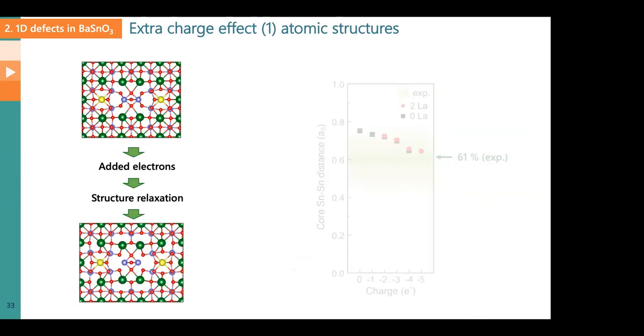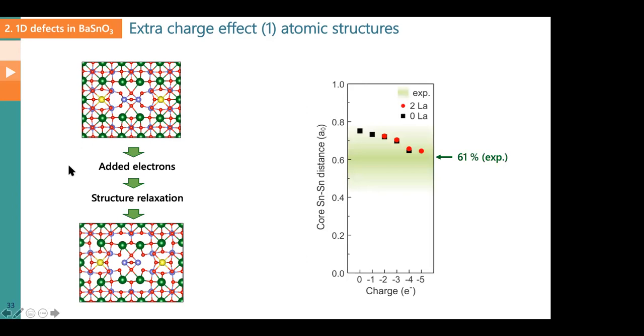So what we did next was to say, okay, if these bands are available, what if I add more electrons to the material? If my defect is truly metallic, all of the additional electrons need to get sucked into this defect. So that's what we did. In our simulation, we added one electron at a time and saw what happens. Then we added a few more electrons. Actually, now the bond distance got an almost perfect match with the experiment, which means we're on a really good path. Experimental data and theory are now matching within only a few percent.